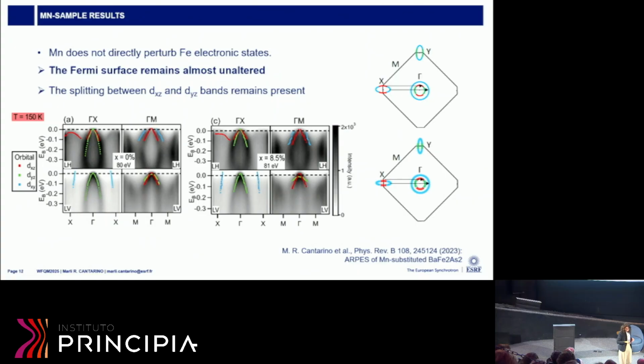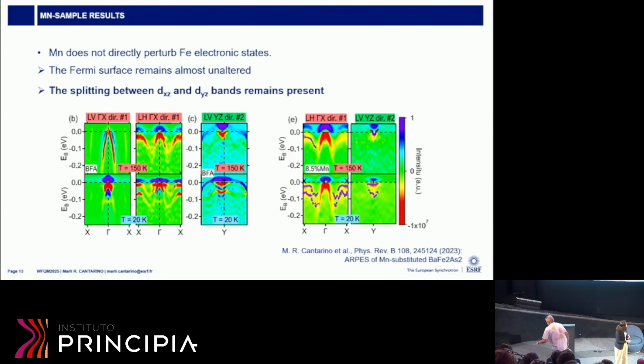Another thing we saw is that when you go to the 8.5% manganese doping, you still have the splitting between the d_xz and d_yz bands, which is characteristic of the orthorhombic distortion and the nematic splitting of these orbitals. So in this sense, there was not much difference when we dope between the parent compound and the 8.5% manganese sample. The biggest difference was in the incoherence and the width of the spectral function.